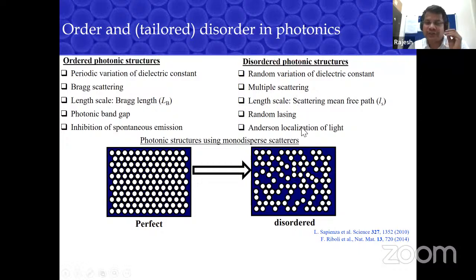Okay. So I'll show you some of our initial results in these directions. We start with perfect photonic crystals, like our sample which I showed you, a very nice one. And we do something to the system, again chemically, we create some kind of disorder which is not quite random, but locally they are connected. What we call short range ordered systems. This is quite interesting in recent years. What we call tailored disordered systems, and there are claims that tailored disordered samples even outperform the ordered systems. Okay, so let's see how we do that.